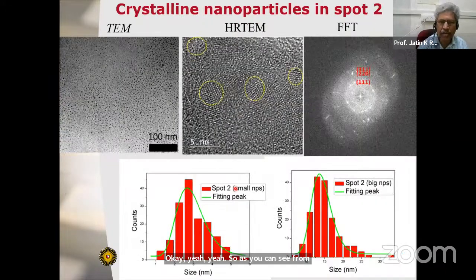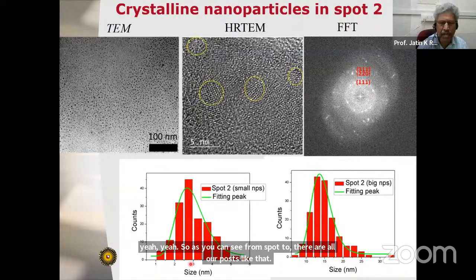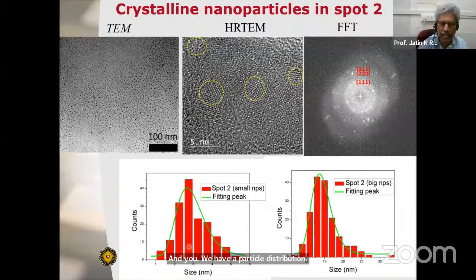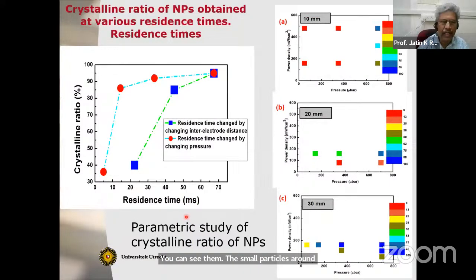So as you can see from spot 2, they're all amorphous like that. And we have the particle distribution. You can see them. The small particles are around 2 nanometer. These are all quantum dots. And what you can see is that the residence time determines the particle crystalline size, the crystalline ratio of the material. How much crystallinity there is in the particles which are formed depends on the residence time of the gas. The residence time can be changed either by the plasma volume or by the gas flow. So this way we can control the crystallinity of those particles.